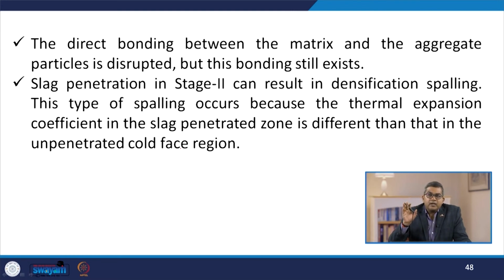This type of spalling occurs because the thermal expansion coefficient in the slag penetrated zone is different from that in the unpenetrated cold face region. So, on continued thermal excursion, maybe cooling or heating, spalling can occur at the line of demarcation between the penetrated and unpenetrated areas. The residual lining after spalling then begins the corrosion process anew, progressing from stage 1 to stage 2 again.